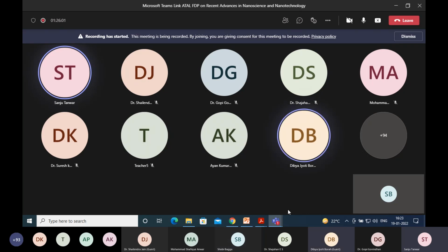Sir, I'm working on metal oxide quantum dots for gas sensor applications. My question is this: when the sensor operates at a temperature less than 100 degrees Celsius, the effect of relative humidity on the target gas response properties is significant. How do we measure the relative humidity effect of a sensor to a target gas?